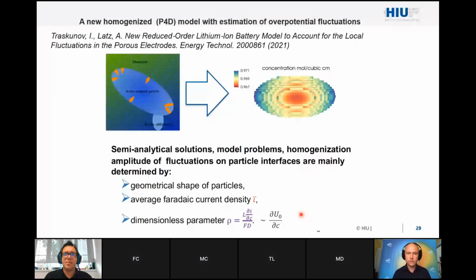So we have this, as I said, a rigorous model. It's a rigorous upscaling procedure. We have semi-analytic solutions for the fluctuations on particle interfaces, and we have shown that it can be calculated now as efficiently as the P4D model, but gives in addition the size or the scale of the expected fluctuation and therefore the probability of degradation events.